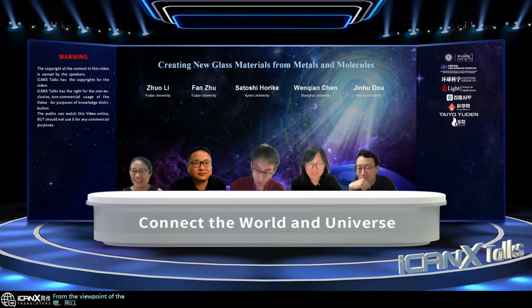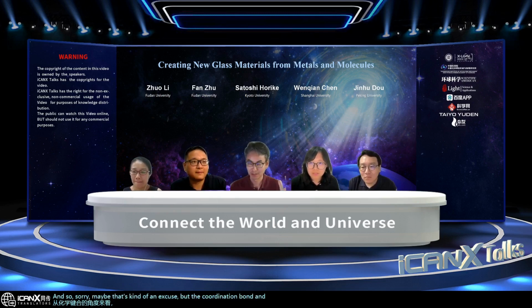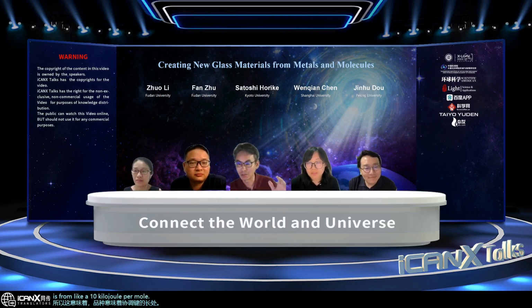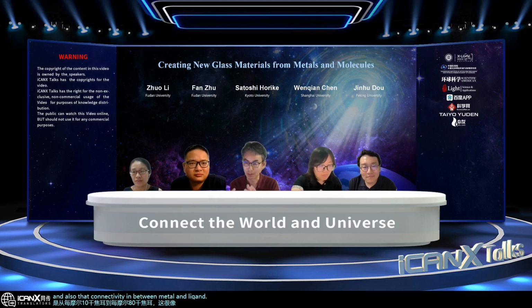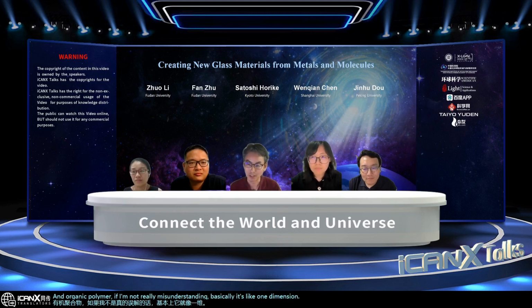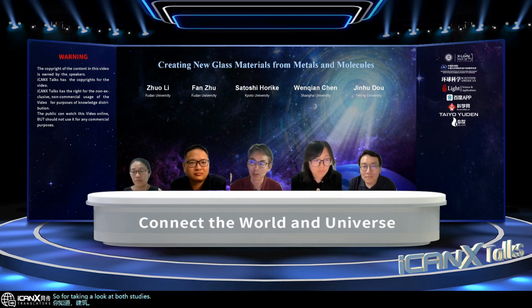From the viewpoint of chemical bonding, the coordination bond has quite a variety of types, with bond strength from about 10 kilojoules per mole to 80 kilojoules per mole, which is quite a wide range. The connectivity between metal and ligand, as I showed, is also quite different. On the other hand, metal oxide usually uses tetrahedral systems, and organic polymer, if I'm not misunderstanding, is basically a one-dimensional architecture. So considering both the coordination bond strengths and the structures that form the glass, I hope we can say it's really a new type of glass.